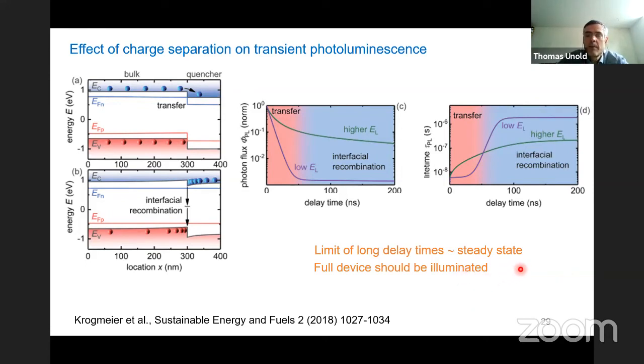That's something Susanne mentioned. So for that case, you have to make sure you illuminate the whole solar cell and not only a partial solar cell. So in a partially illuminated solar cell, you may have charge transfer effects also in your steady state PL, but if you illuminate the whole solar cell, this is not the case.